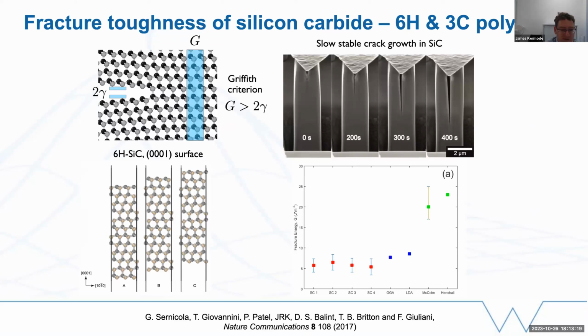If we think about fracture, it's a thermodynamic process. We've got energy flowing from some region that's stretched ahead of a crack tip through to the creation of open surfaces. And there is this Griffith idea going back nearly 100 years now that fracture is favorable when the energy that is released by unstraining a region exceeds the cost of creating these surfaces. So G is bigger than 2 gamma. And in principle, to calculate that, all we need is the elastic properties and surface energies. And that can be done directly with density functional theory in small model systems.